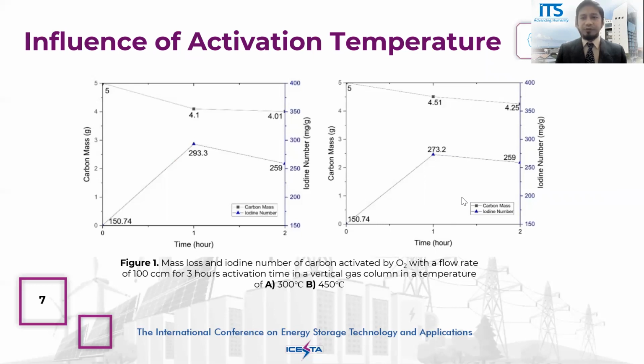The objective of the activation basically is to decompose the carbon slowly, in such a way that the black carbon can form a fibrous morphology as activated carbon. The temperature variable used in this work was below the onset temperature or maximum temperature of its decomposition, which was obtained earlier from the TPD and TGA analysis conducted in our previous work.